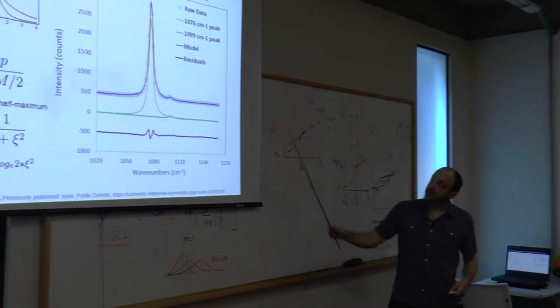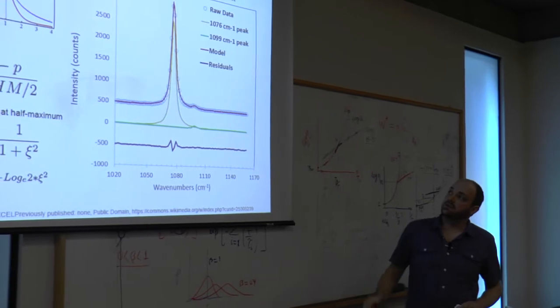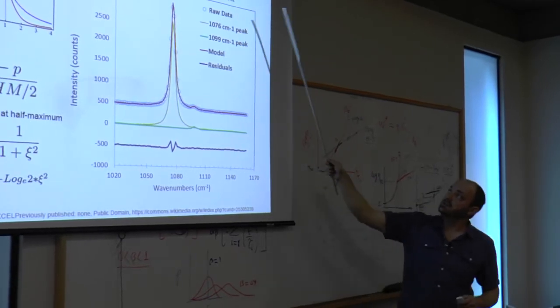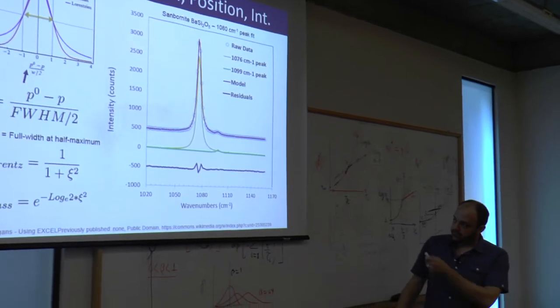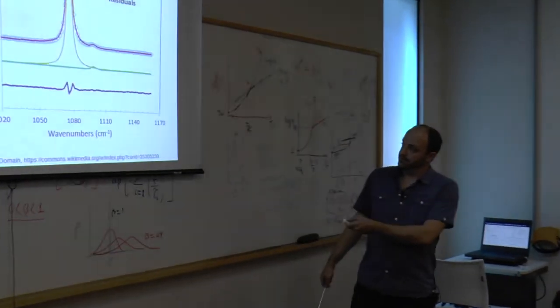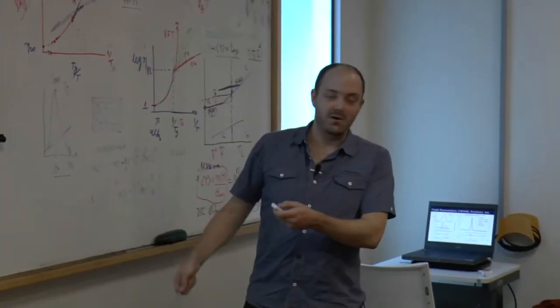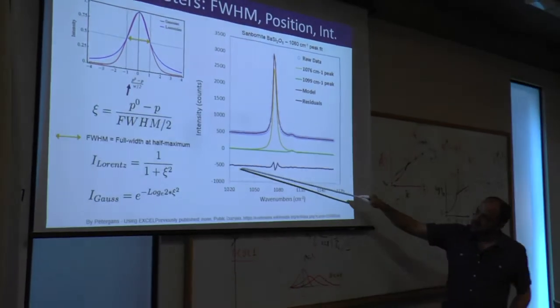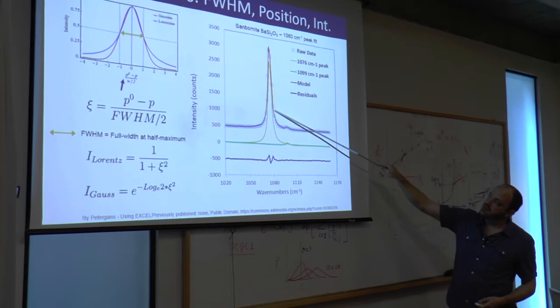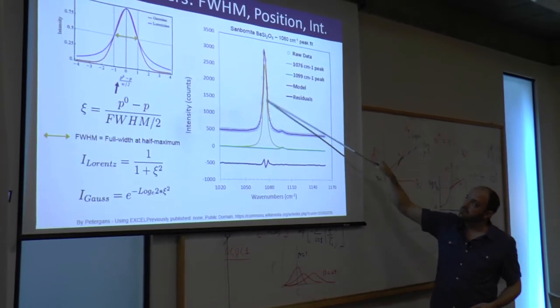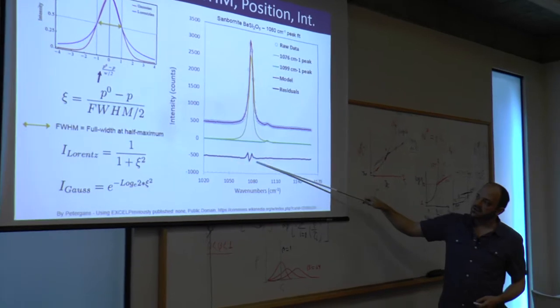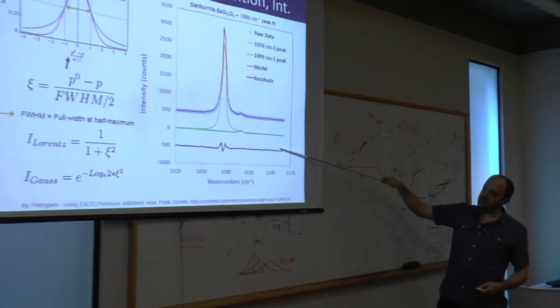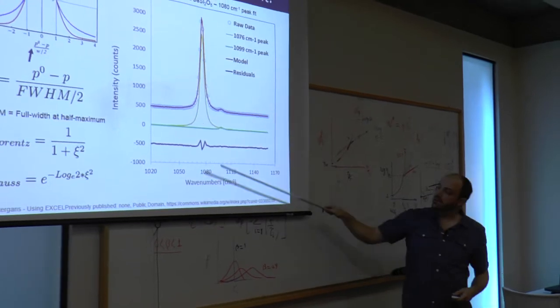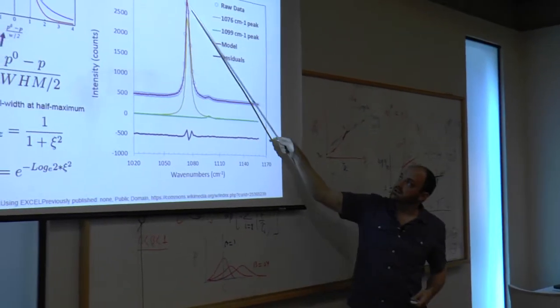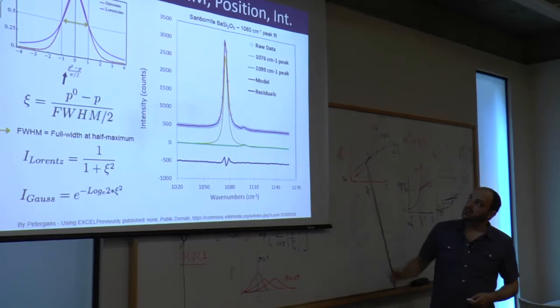But know that the three main important factors for looking at each peak are its full width half max, its position, and the relative intensity. And those are the equations for actually determining them. Luckily, there's a lot of programs for this, so you don't have to do it all by hand. The last feature is a lot of spectra will be published with the residual. So this feature down here, this purple line, is the difference between our actual data points and this red model as it goes through. And you can see there's almost no residual for most of the spectra except right at the peak. So a little bit of a wiggle in the residual is just because of the resolution of the spectrometer and the difference there between the model and the actual peak.